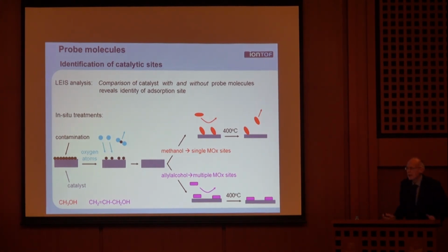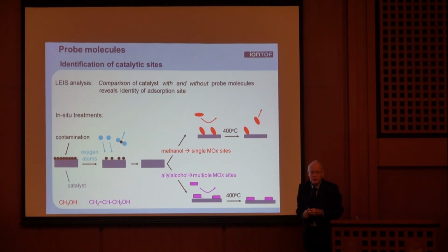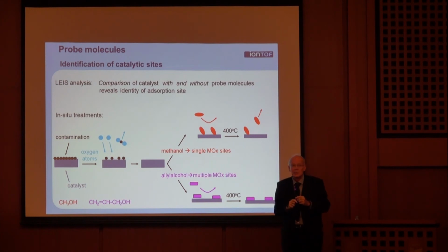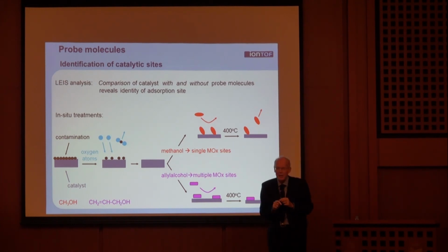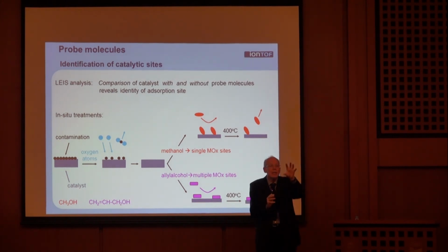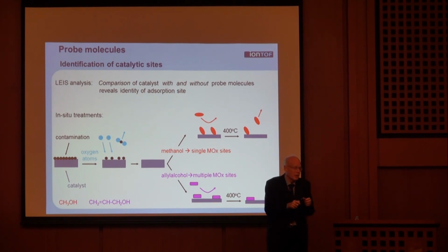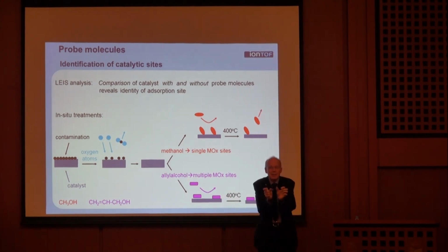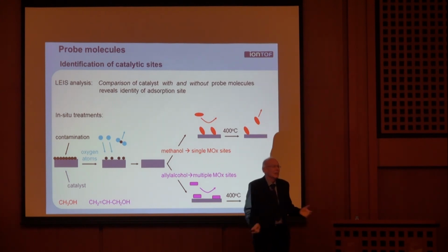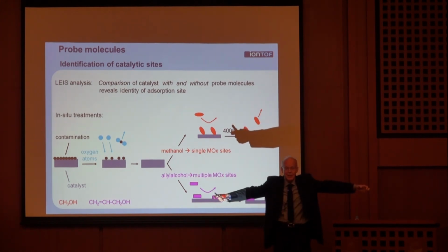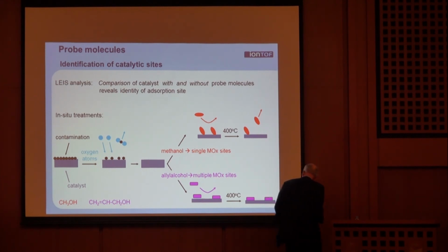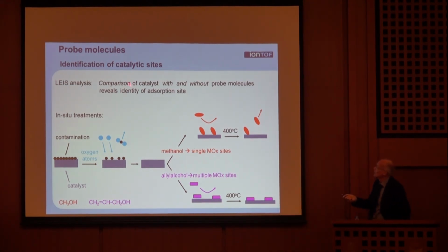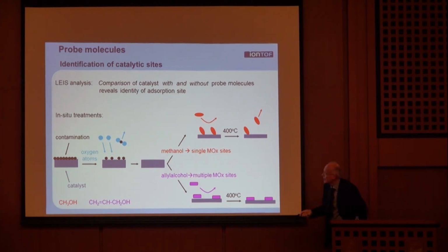Other thing. In chemistry, you are always interested in what is the active site. Well, generally we don't really know very much about the active site. But sometimes you need more than one center next to each other. So we looked at catalysts where, for instance, you need two vanadium cations close to each other with a certain valence state. And so how can you find out whether they are far away or next to each other? One of the ways you can do that is by using probe molecules. For these probe molecules, I can use either methanol or allyl alcohol.